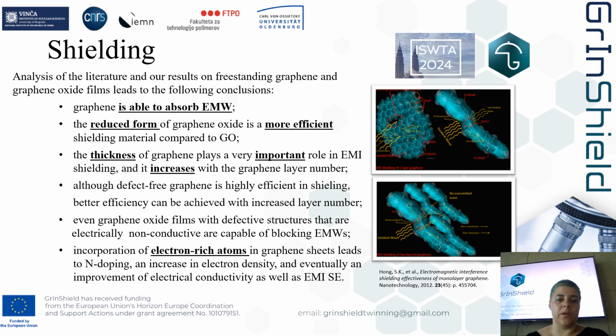Some of the literature that we have been studying in preparation for our project exploitation and creating the graphene oxide films and freestanding films and reduced graphene oxide freestanding films that we were able to produce. We studied a lot of literature, and some of the conclusions that both the literature and our preliminary results have led to is that graphene is able to absorb electromagnetic waves, and the reduced form is more efficient in shielding than the graphene oxide. The thickness plays a very important role, and the shielding effects increase with the graphene layer